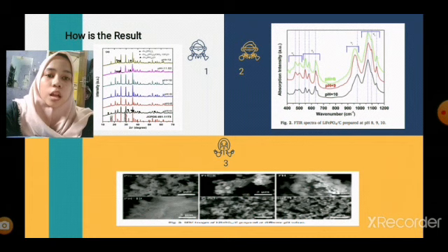In the range of pH value from 8 to 10, XRD patterns show the greater the pH, the stronger the intensity and the sharper the peak. Thus, the higher the crystallinity.